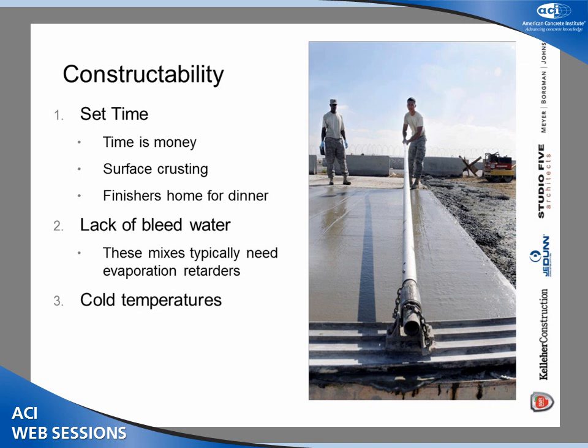Here's some of the issues that we've seen. Surface crusting, and I'm going to talk about that in a little bit. Keeping that surface alive, partly due to the lack of bleed water. Again, like I mentioned, finishers home for dinner, lack of bleed water. These mixes typically need evaporation retarders. And then, of course, the set times that are problematic are only exacerbated in the winter when it's cold. Cold temperatures exacerbate the situation.